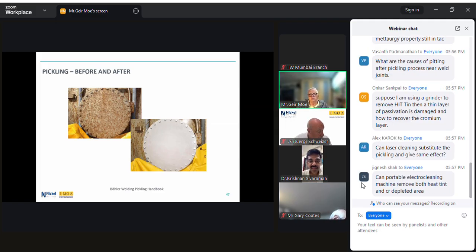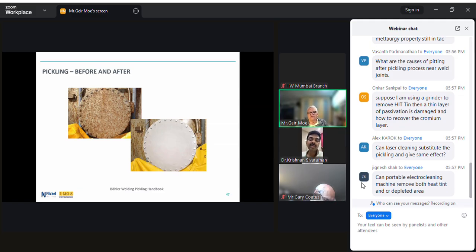Generally, you would want to do a passivating treatment after blasting to make sure that you're removing any potential contaminants that could have been forced onto the surface from the blasting medium. So what you are telling is you will not be able to replace the pickling passivation, but it has to be done post the blasting, correct?